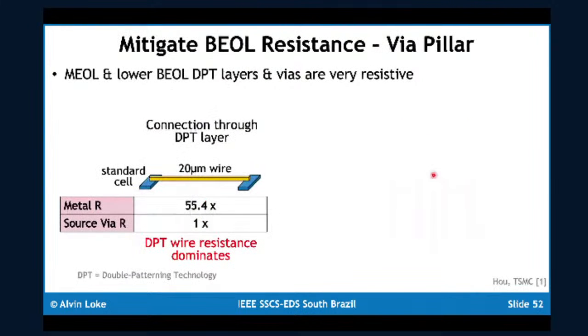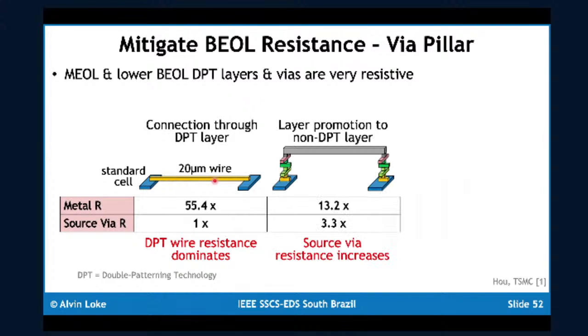Via pillars or layer promotion can be a very valuable trick to reduce resistance. As I mentioned earlier, because the middle end of line metallization is so resistive, if you have long routes, it might actually be better for you to layer promote to a much more conductive metal layer at the top.